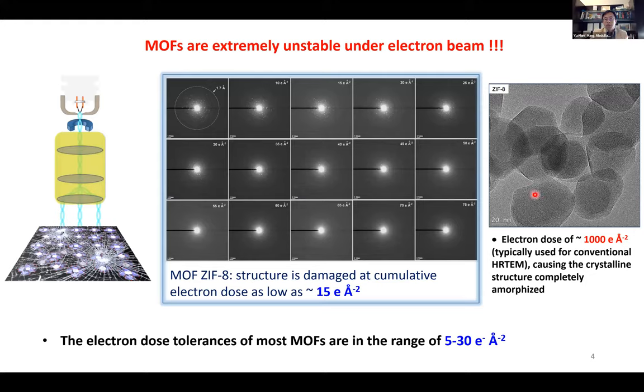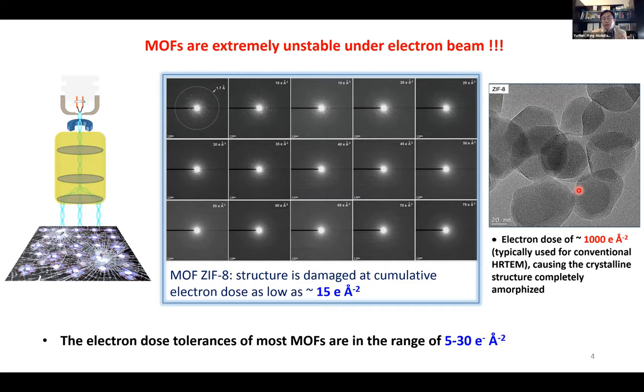Here is an example to explain the beam sensitivity problem. This is a TEM image of ZIF-8 acquired with an electron dose of about 1000 electrons per square angstrom, which is a very typical dose used for conventional HRTEM. However, under these typical conditions, the ZIF-8 crystalline structure has been completely destroyed by the electron beam. What we see are just amorphous particles without any useful information, which is why conventional HRTEM is not suitable for imaging sensitive materials like MOFs.